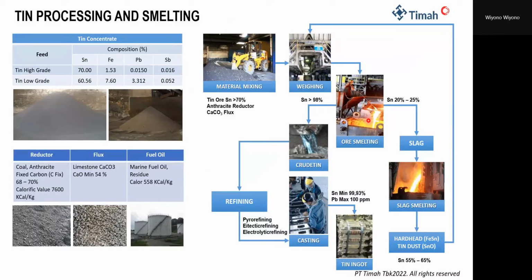Okay. Tin smelting has two stages. This one is the first stage. In the first stage, we smelt the tin concentrate, and the output from the first stage of tin smelting is crude tin with tin content more than 98%. Besides crude tin, we also get slag with the Sn content from 20 to 25%. We also get tin dust from tin smelting, and we will recover the tin dust into our smelting to get a higher recovery. And then after we get crude tin, we do the refining process to get more pure tin.